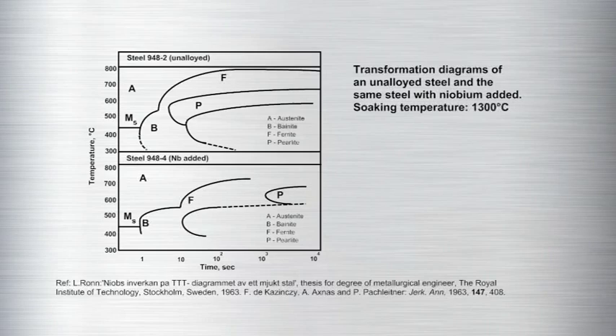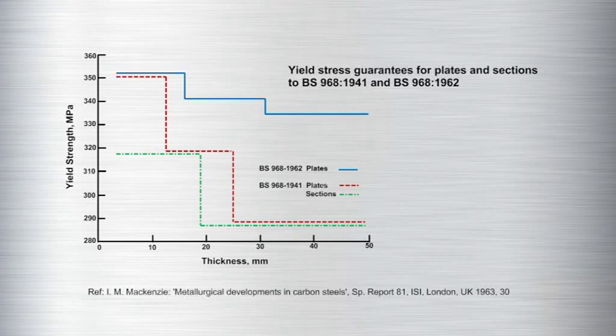It was because of the research both at Sheffield and in Colvilles that the research labs had sufficient knowledge and experience to go ahead with the full-scale production into the marketplace with hot-rolled and also heat-treated steel plates for the structural steel market. Other companies in the UK followed suit, and there were sufficient results obtained that by 1962 it was possible to introduce a new British steel standard, BS 968, which allowed the microalloying addition of niobium, which allowed an increase in strength over the previous specification, but also a better weldability because it reduced both the carbon